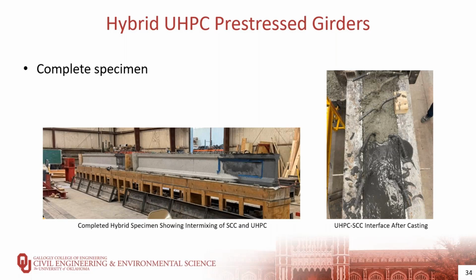Here you can see that there has been some SCC flowing into the UHPC end in the bottom flange, and this was the first set of the beams. So we're still trying to evaluate and to control the flow rate of the SCC to get a better interface between those two concretes.